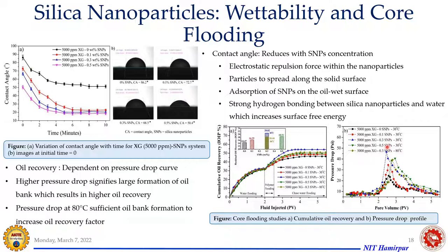And you can see this pressure drop range is what we got when we injected this nanofluid at a certain pore volume. So 0 to 2 pore volume is only water flux, until it reaches a stagnation point, and from 2 to 2.5, 0.5 pore volume is the optimum slug we have received. So you can see this is the effect of this 0.5 slug, which is why the pressure drop is seen here. A higher pressure drop indicates the formation of an oil bank, and as we go on increasing the concentration beyond this optimum, you can see it is not going back to its normal condition. So there is a certain lag in this pressure drop curve. This shows there is a blockage of the pores, and that's why it is not going down to its initial condition. So you can easily identify that there is a pore blockage. Okay.